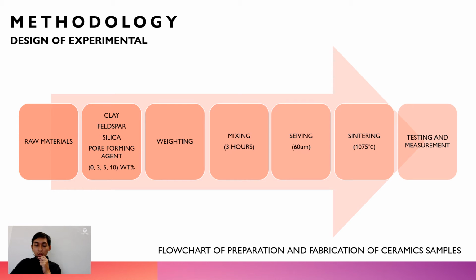Next, we continue on the weighing process, where each material will be weighed accordingly. After the weighing process is complete, we continue on the mixing process, where the mixing will run for 3 hours for each level of content. After the mixing process, we continue on the sieving process, where the sieving apparatus will be used at 60 micrometers. After the sieving process is complete, we continue on the sintering process, where we will bake the ceramic samples at 1075 degrees Celsius for 3 hours. And the last process of this research is testing and measurement.